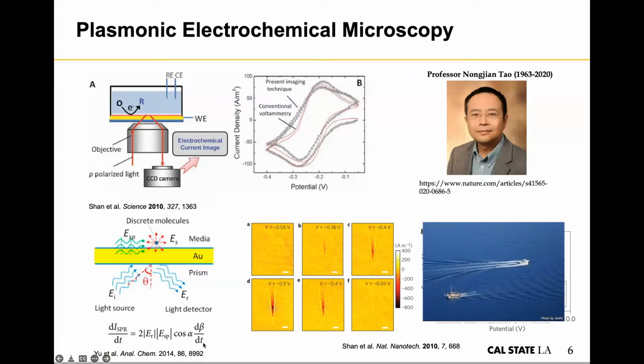And also, because we assume most of the time the optical property change is proportional to the electrochemical reaction per time, by simply using this relationship, we sometimes assume that by simply taking the derivative of the intensity at the local particle, it's proportional to the current density change at that nanoparticle. So without doing a very complicated conversion, the SPR image can be converted to a plasmonic current image, which can be correlated to electrochemical reactions. Okay, so this is a brief introduction of how this technique works.